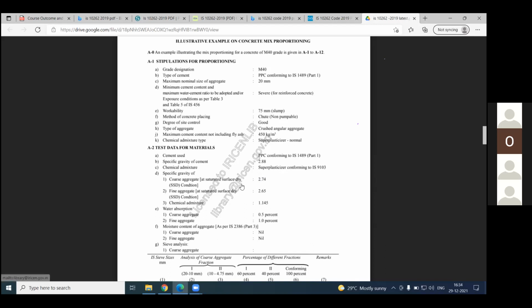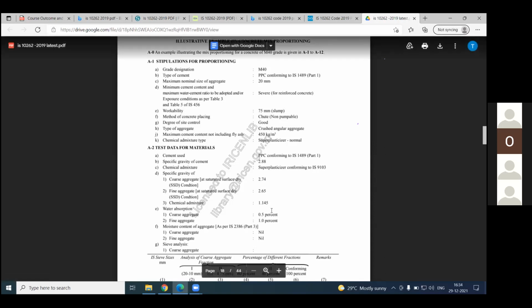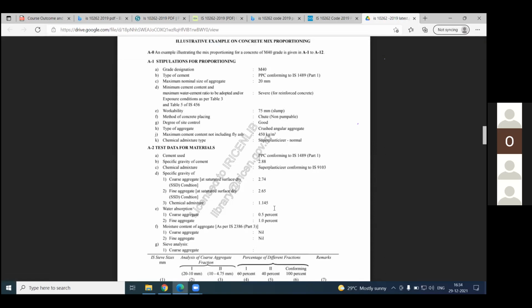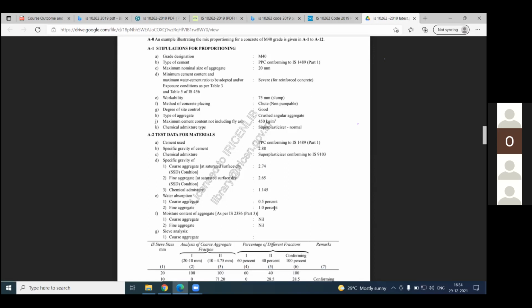For each material, we will get the specific gravity of aggregates in SSD condition and saturation condition, and the admixture weightage, and the water absorption of the coarse aggregate and fine aggregate. Due to this water absorption, we can deduct or increase our water content. If we have a lot of moisture content in the aggregate, then we have to reduce our water content so that the workability will be maintained in a proper manner.